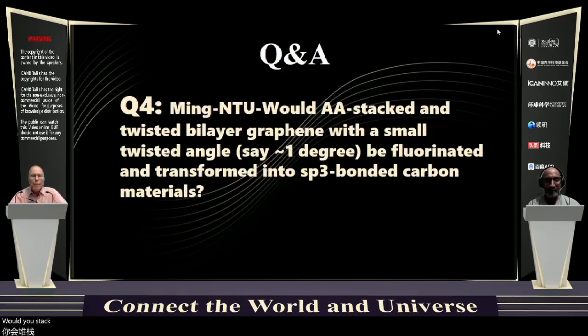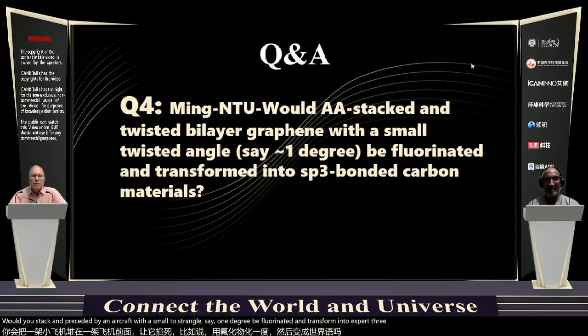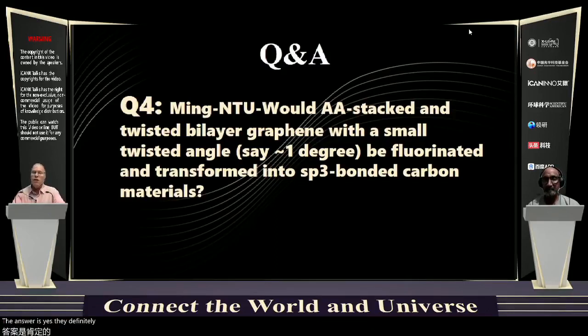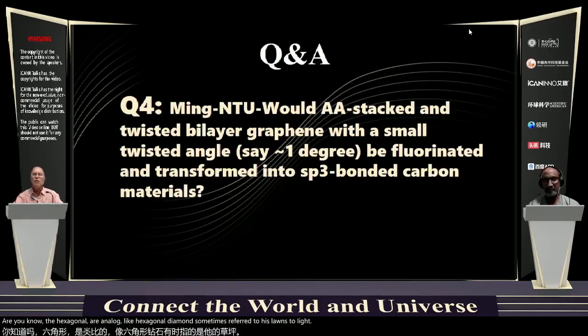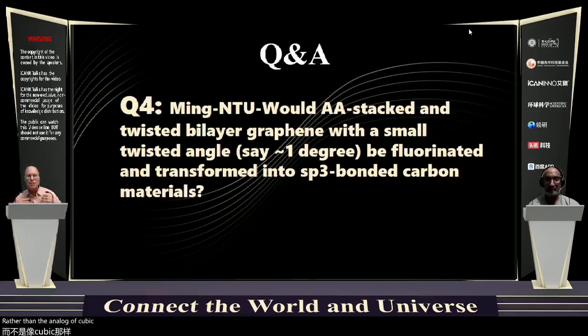Thank you, Rod. So the final question is from Ming from NTU. Would AA-stacked and twisted bilayer graphene with a small twist angle, say 1 degree, be fluorinated and transformed into sp3 bonded carbon materials? The answer is yes, they definitely would be. If we could somehow configure the layer stacking to be AA, which is nominally metastable, right at the cusp of transition between AB and AC. But it's possible to achieve AA by techniques like folding over small regions, which has been observed in TEM. Without doubt, the calculations suggest that fluorination would drive interlayer bonding and we would have the hexagonal analog like hexagonal diamond, sometimes referred to as lonsdaleite. We'd have that as a single layer rather than the analog of cubic diamond, which is what our team made.